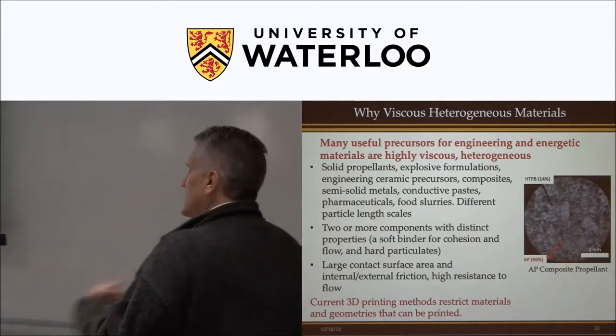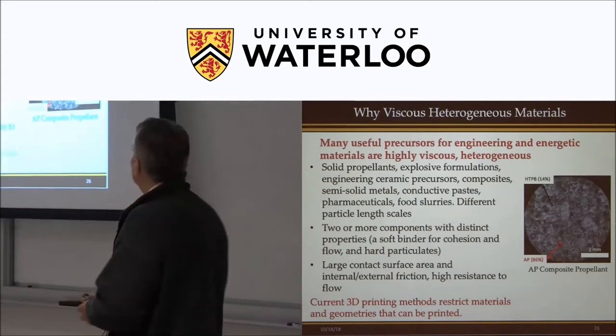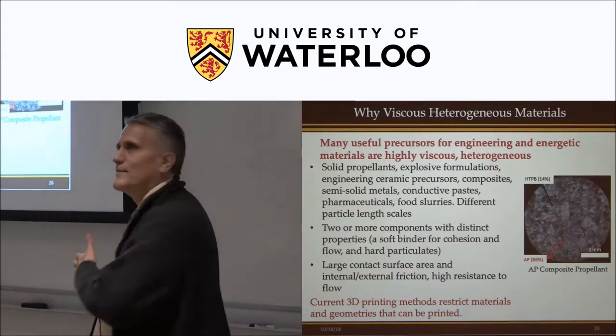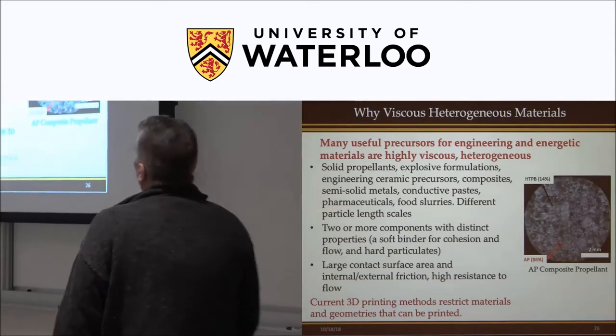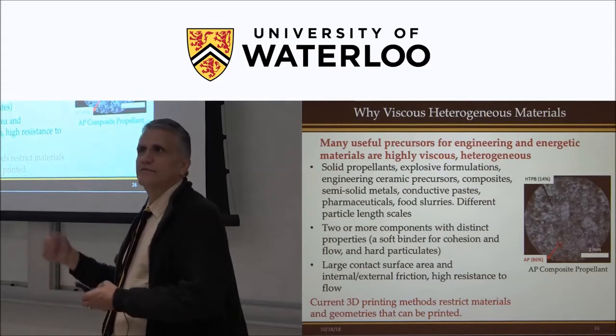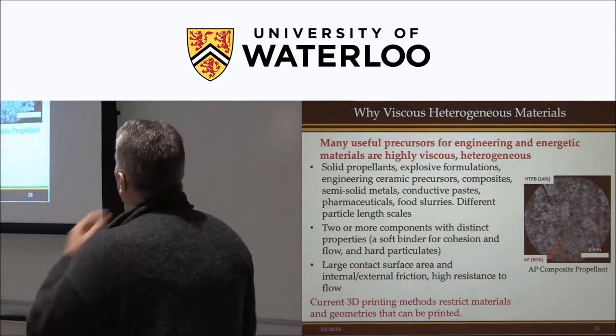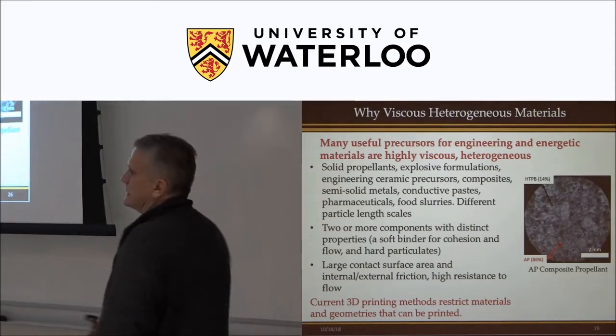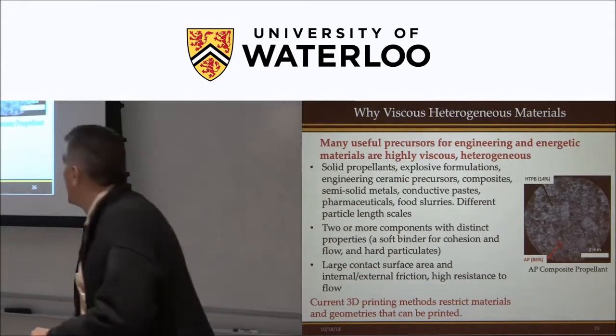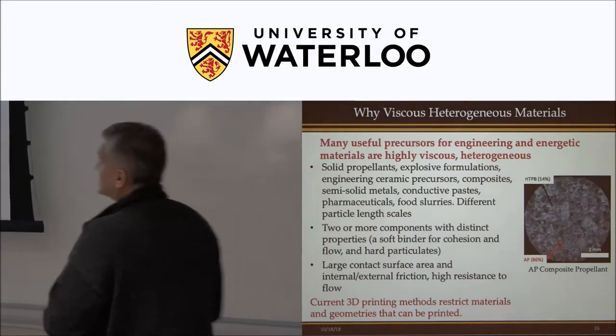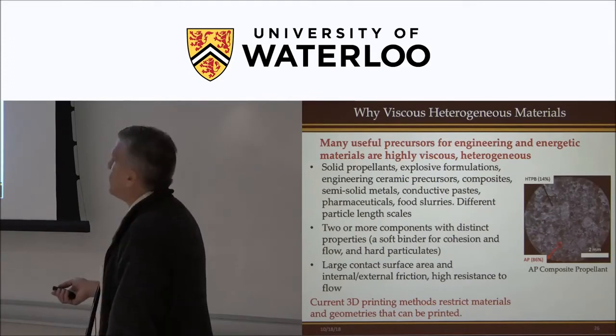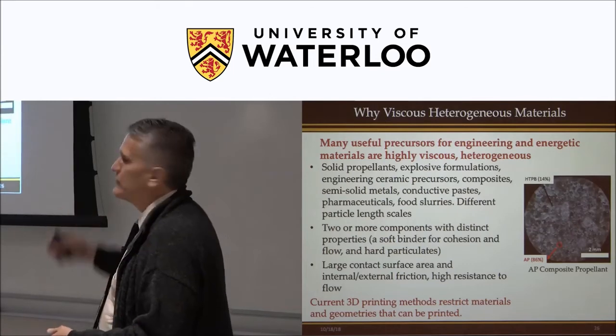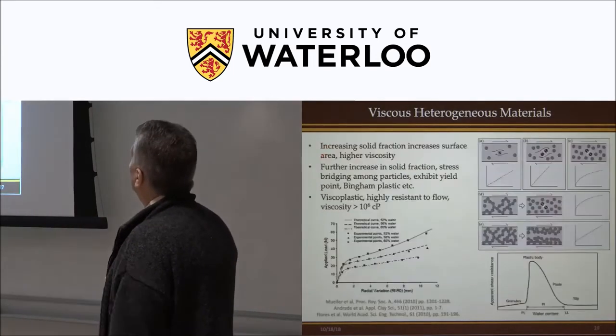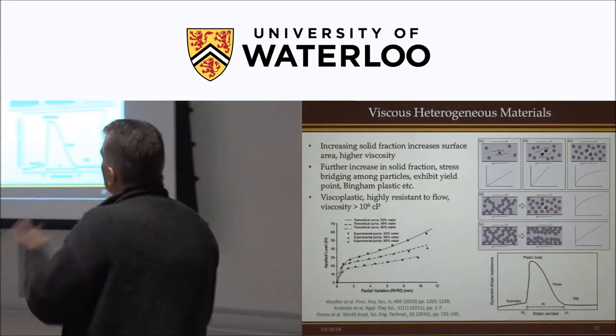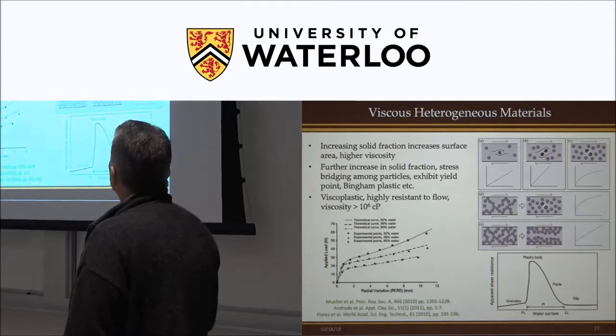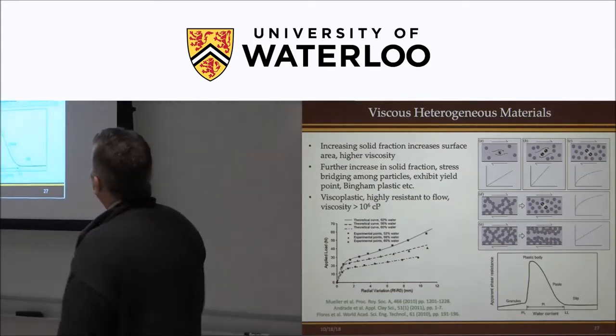These materials are highly viscous. When you mix up a solid propellant, think of that as like cookie dough. It's quite viscous, especially if you're trying to maximize the amount of sugar in your cookies, right? And here, we're trying to maximize the amount of oxidizer in our propellants for performance. Well, that works against being able to deposit that and build up 3D structures. So that's challenging. The current 3D printing methods restrict the kinds of materials. We really can't use the binder, the polymeric component holding this together, that we'd like because the viscosity is too high. We'd like something thermal-softening that will work better, or we will have to restrict the amount of solids in the propellant, giving a poor performing propellant. Increasing the solid fraction increases the surface area that has to be bound together with the binder, and the viscosity increases with that. And I think I'll move along.